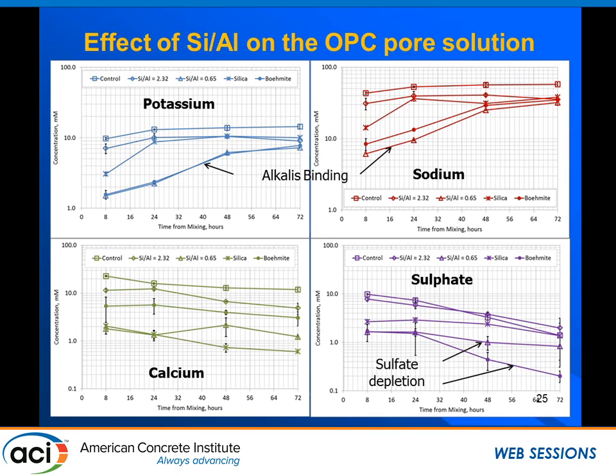What's happening here is that we measure the pore solution, and the top ones in all cases are only cement. The triangle ones are the 0.65, which appears to be the optimal. We see that 8 hours after mixing, there is quite a difference in the potassium and sodium concentration in the pore solution. It appears that there is alkali binding. Over time, this difference decreases, and it appears that the alkalis are going back into solution.